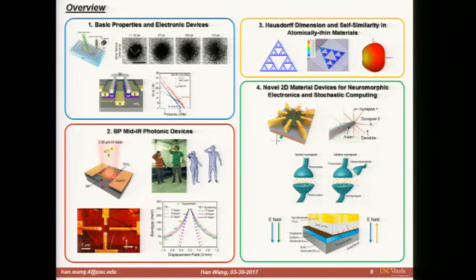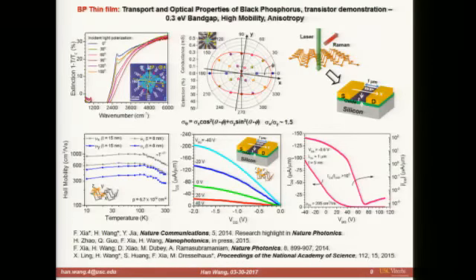Some of these new device ideas also make use of the anisotropic properties in black phosphorus. This slide summarizes our earlier work in 2014 and 2015, studying the optical and electronic properties of thin film black phosphorus, about 5 to 20 nanometers thick, across 6 samples. This includes measurement of the extinction spectrum showing anisotropy, anisotropic DC conductivities, Hall mobilities, and demonstration of one of the very first transistor devices based on these materials.